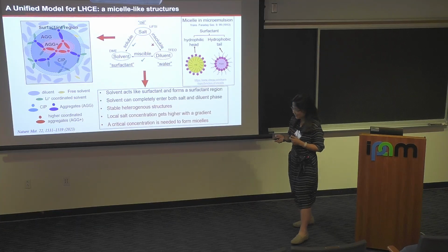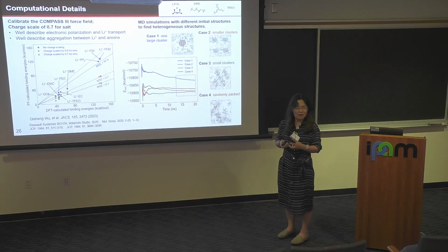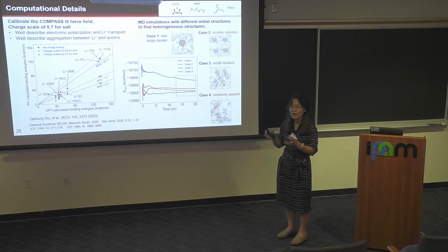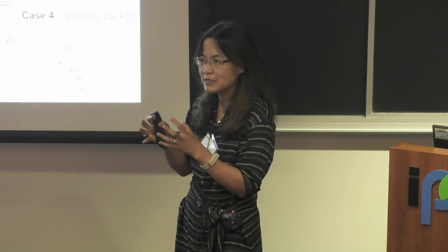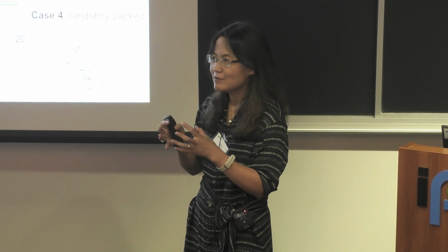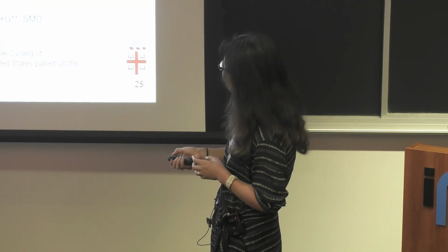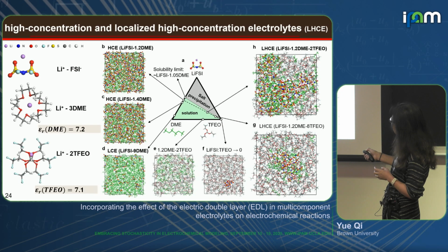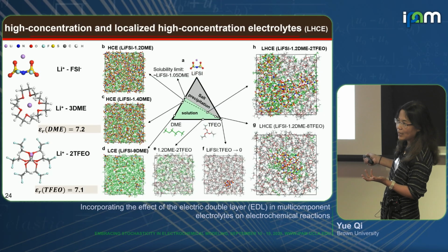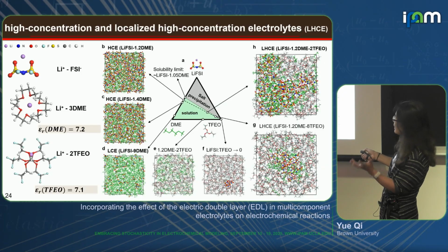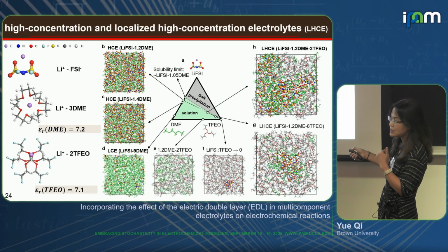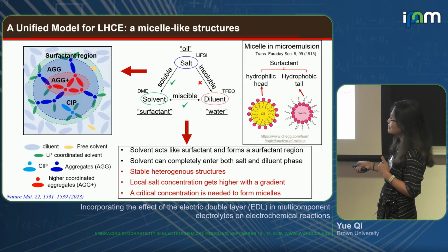I keep asking the experiment group, I said, you have phase segregation, you have nanoclusters in your solvent. Why doesn't your salt and solvent cluster segregate, right? So we see this, the salt and solvent cluster in this diluent phase. I forgot to mention, this one doesn't like each other, and this one likes each other very much. If you put all three together, what's going to happen? In the literature, people have been talking about the salt and solvent cluster dispersed in this diluent matrix. I was just wondering why they don't collapse.